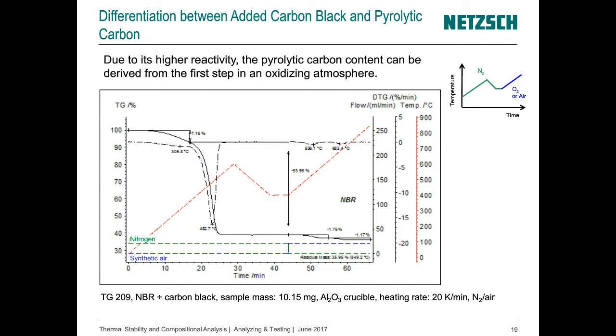And such a modified temperature program you can see here on this slide, and here we go up at first in the first heating step up to 600 degrees C in nitrogen atmosphere, then we cool down a little bit again down to 400 or 300 degrees C and keep this temperature constant for a while, everything still in nitrogen, and then we switch over to air or oxygen, so that means to oxidizing conditions for combustion. And if we do like this, then we can see in the final oxidizing step two mass losses. In this case, one of about 1.7 and something percentage, and a second one of about 1.2%.